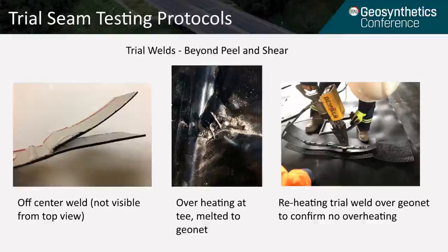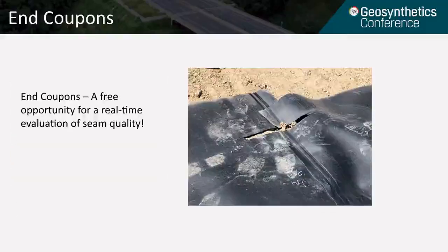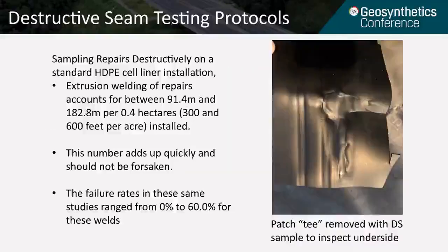Trial seams are a great opportunity to evaluate the welds beyond peel and shear. You can look for off-center welds, overheating at tees, make sure the material is welded on top of the proper material. It's a great opportunity, but often it's not used because it's not in the specifications. End coupons are another way to get a real-time glimpse into the quality of the weld and should be put in the technical specifications. Destructive seam testing protocols should include the testing of repairs.